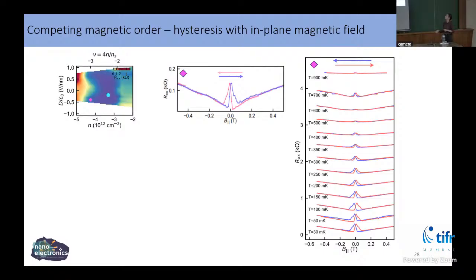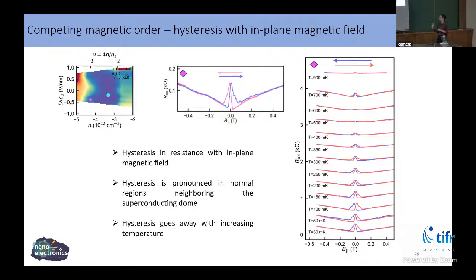Not only that, we also studied these hysteresis features with temperature, and they vanish as I increase the temperature. That gives you a scale to compare both the superconducting order and the magnetic order. Interestingly enough, there is also magnetoresistance, which is that the resistance of my system increases as I apply a magnetic field. That also independently points to the presence of a magnetic order. If you look carefully, there is hysteresis and there is magnetoresistance. But when I go here, there is no hysteresis and also no magnetoresistance, which tells me that these two things are connected in some way. The disappearance of the hysteresis also connects to the disappearance of the magnetoresistance.